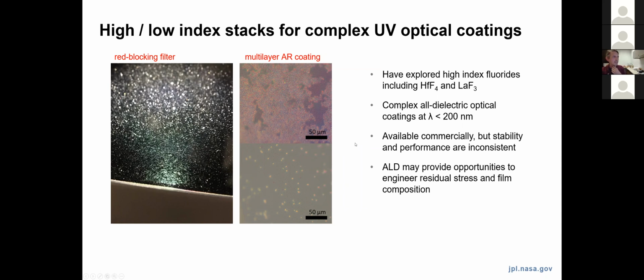And the takeaway is that although you can buy some of these types of coatings commercially, there's still a stability and performance issue. So these are just some examples of test coatings developed for flight projects at JPL or Caltech that experienced unexpected degradation, let's say, as a function of primarily, again, humidity exposure. So ALD might have some opportunities to engineer some improved stability into these coatings.